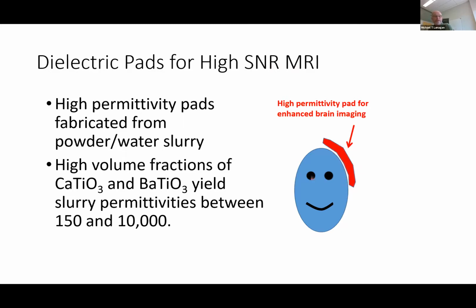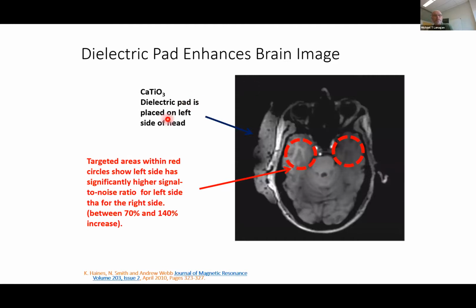The permittivity values I'm talking about are somewhere between 150 and 10,000. Just for reference, the permittivity of water in the head with all the other parts of the brain is somewhere between 50 and 70, depending on the frequency. So we have something that's between 50 and 70 for the permittivity, and we're trying to couple in this higher permittivity. And I'll talk about the physics of this in a minute. But essentially what we can do is we can look at the geometry of this dielectric pad, say, for example, the thickness, and we can look at the permittivity and optimize it to get the signal in and out of the head.